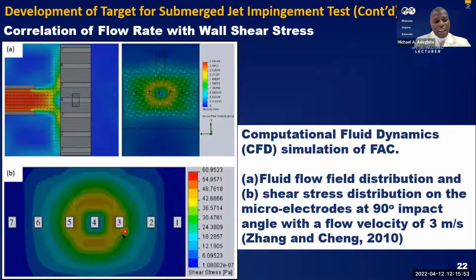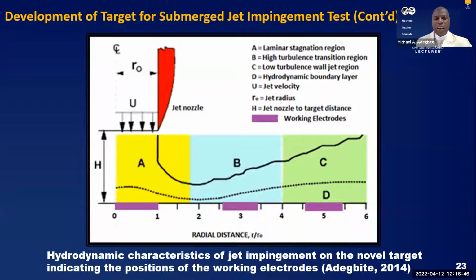And then a radial distance associated with twice the radius of the nozzle is where we have high turbulence. And then moving radially outward, we can see the typical flow pattern in terms of low turbulence. And that shows that when we have flow, there are some regions associated with high turbulence and some regions, especially at the elbows, some regions will be stagnant. And then we also have regions with low shear stress. And that's typical, and this is used in this particular study.